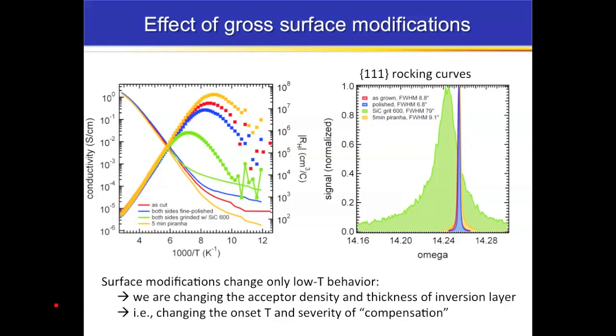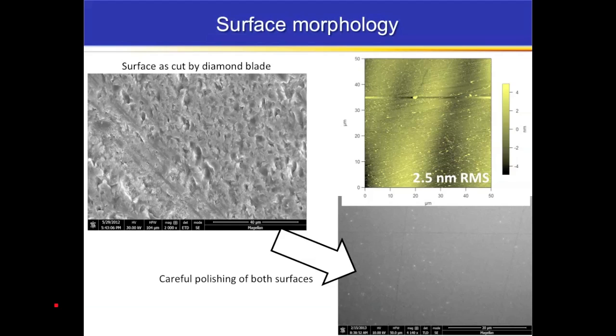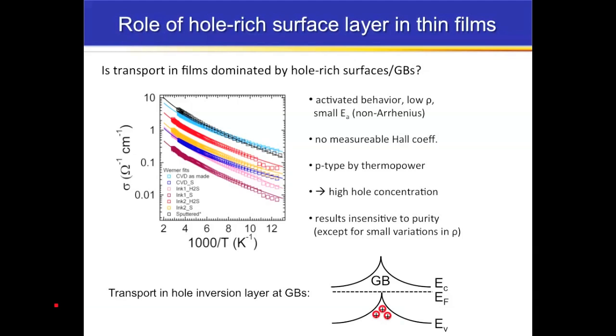We can also use rocking curves to actually monitor the surface damage that we're creating, especially with the silicon carbide roughing paper. This just shows that we can in fact get very rough surfaces. We can get very, very nice and smooth surfaces down to a couple nanometers RMS roughness. And what I want to do now is tie it back finally to the thin film data.